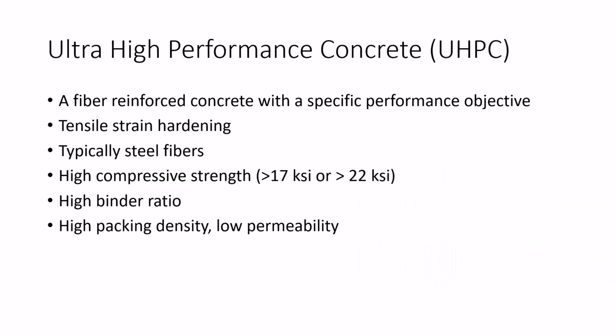The next thing was ultra-high performance concrete, so UHPC. You've probably all heard of this as it's such a popular topic right now. It is a type of fiber reinforced concrete, with the fibers typically being high-strength steel fibers. UHPC usually has a certain performance objective, which is very high compressive strength, something like 22 ksi is possible, which again is not very critical for decks to achieve, but it has that very high packing density and low permeability, so that does make it very durable and does make it attractive for deck applications.